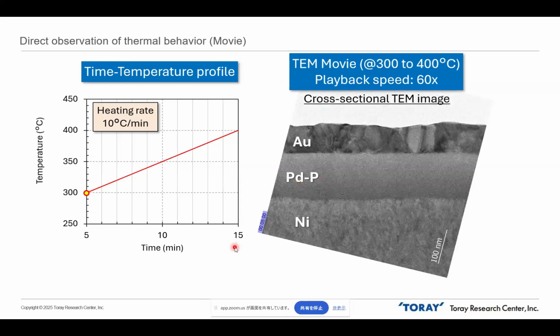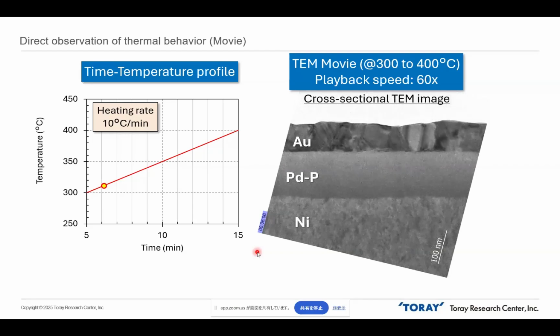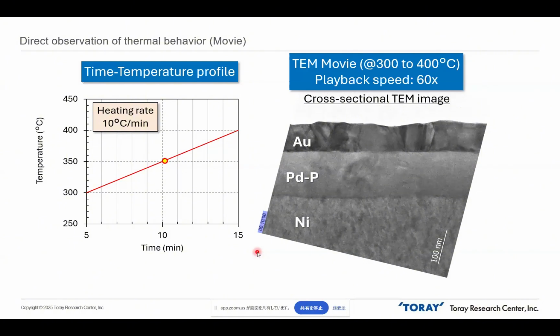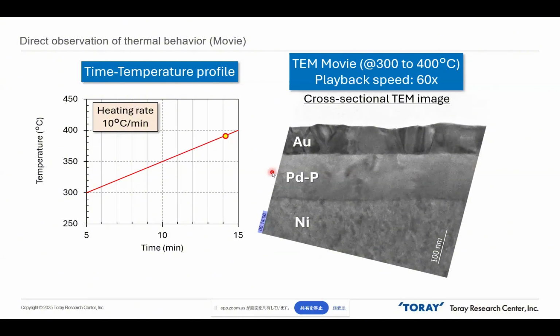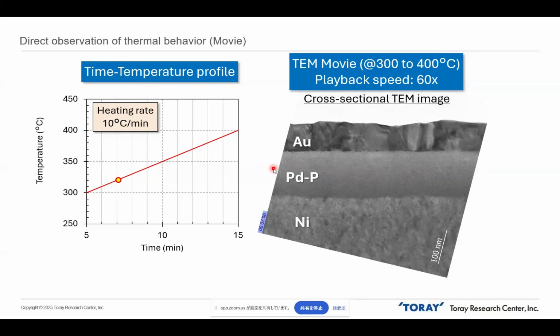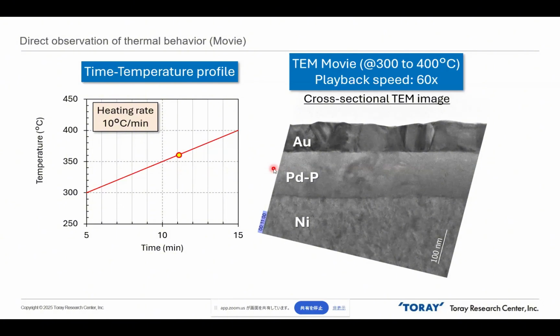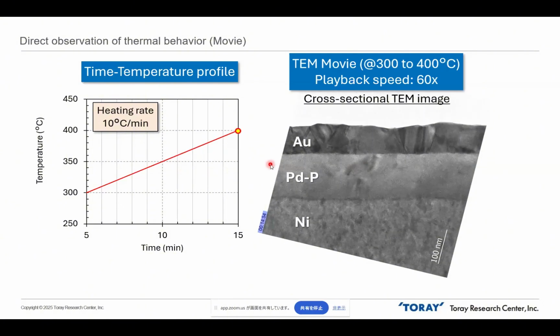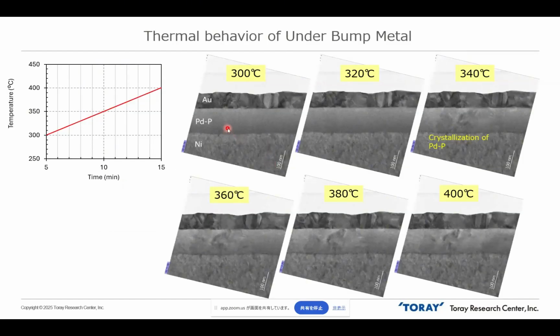So let's see the experimental results. This is the result of just heating, just annealing. Let's see the movie. From room temperature, we apply heat to the thin lamellar specimen. Then maybe you can see the crystallization of the palladium layer. Okay, let's see again. Around 8 minutes, the palladium layer starts to crystallize suddenly. Yes, so the palladium layer is crystallized, at a temperature of 340 degrees.